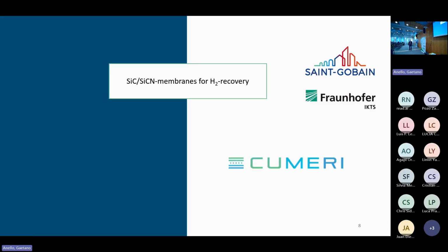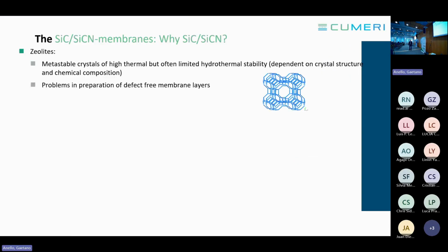the silicon carbide and silicon carbide nitride membranes. Why use this material? There are also other materials possible, of course. There are zeolites, which are crystalline, metastable. Some of them have high thermal stability, but some have limited hydrothermal stability, depending on the composition. And it's always challenging to make defect-free membranes from these materials. It's principally possible, but challenging.